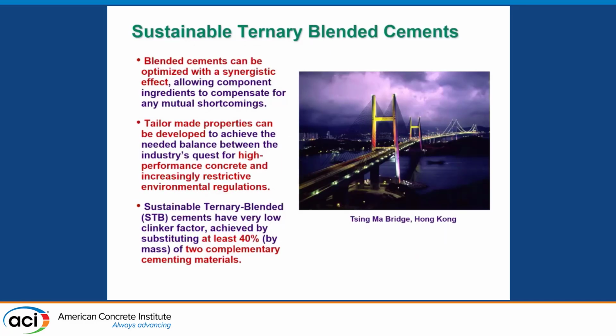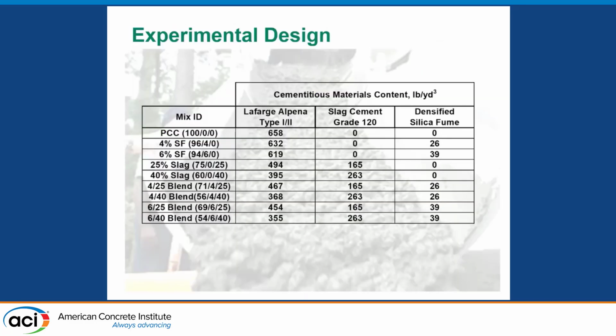So when we looked at sustainable ternary blends, it's really, in my opinion, and Kevin touched on it too, that if you use just enough silica fume, you can really optimize your design. This was the case in something we were doing for the highways in Cleveland, Ohio, and these were really for approaches. So we were looking at a mix that was typically done for these approaches. In our ODOT, our Ohio Department of Transportation, we have different JMFs, as he explained, job mix formulas.